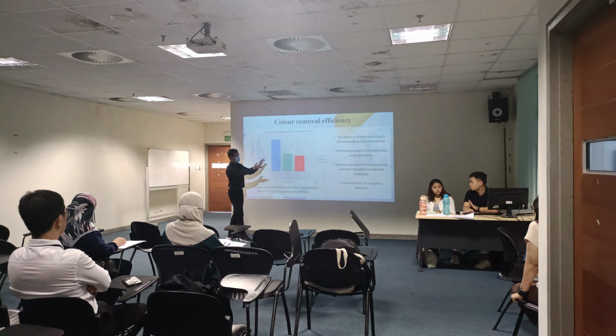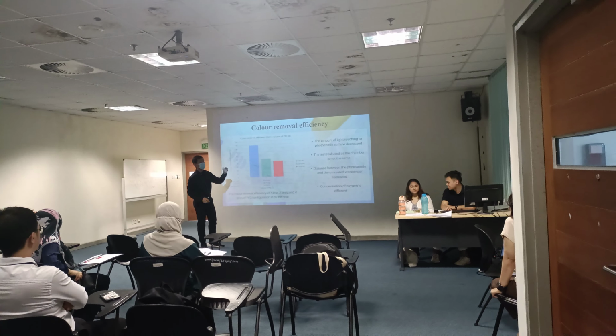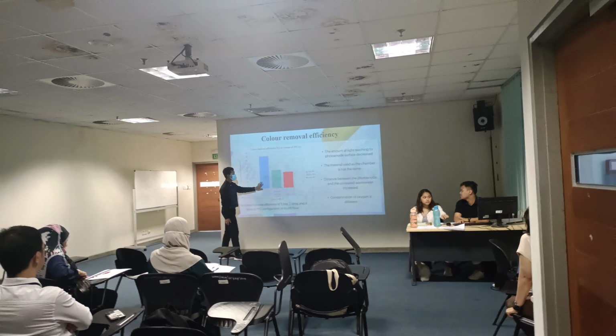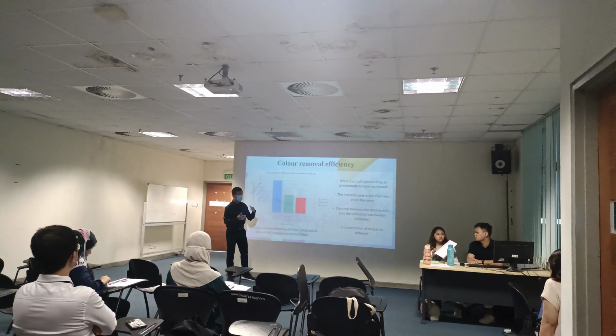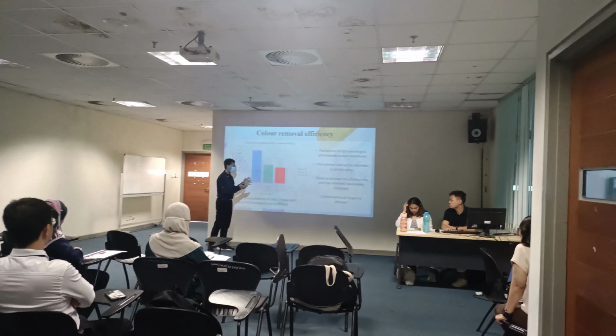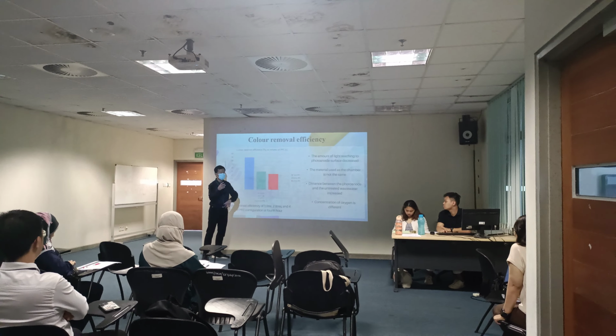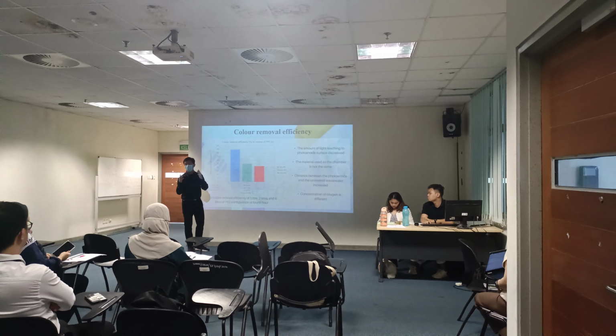After that, the material used for the chamber is not the same either. For the 1 liter PFC and the 2 liter PFC, I'm using polyethylene terephthalate, which is more transparent and has better optical clarity, while for the 4 liters I'm using polypropylene, which allows less light to pass through.